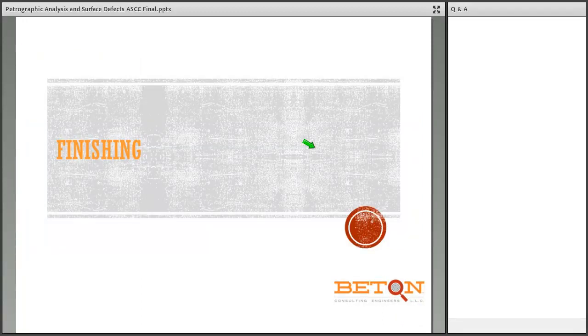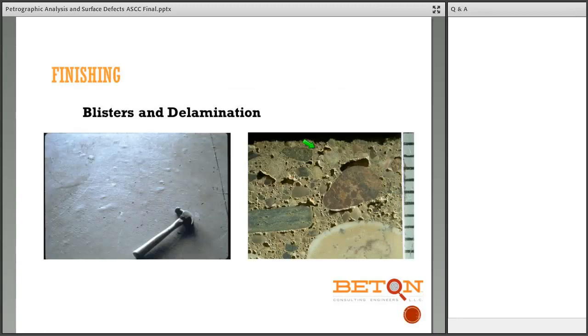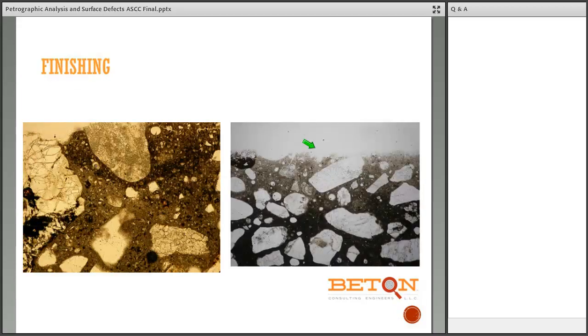Finishing leaves telltale signs in the concrete. We'll see blistering if we have concretes that are still bleeding or worse contain air. We can see that the finishing here at the surface, we have a densified layer of paste that is occurring due to the troweling. And if you look up here, there's a fracture in the paste. That fracture is occurring because of trapped bleed water.